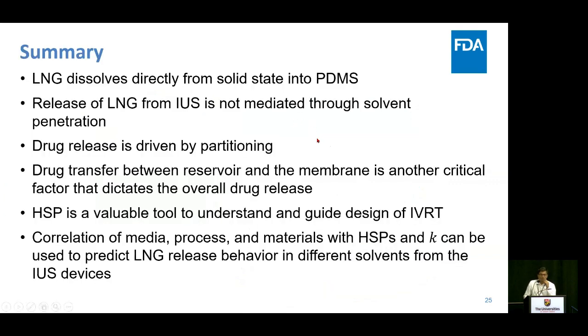So with that, I would like to conclude with my summary that so far we understand that the drug itself, the levonorgestrel, dissolves directly from solid state to PDMS because there is no solvent penetration. And then the release of the drug from the IUS is not mediated by solvent penetration, as the release is essentially mediated by partitioning of the drug. And also the drug transfer between the reservoir to the membrane is another critical part that can be explained by the characteristics of the polymer, and HSP can be helpful in this regard. And also HSP can be a valuable tool to understand and guide IVRT. And finally, by correlating media, process, and materials to HSP and partition coefficient, we can actually predict the release behavior of a drug from a polymer in a solvent.